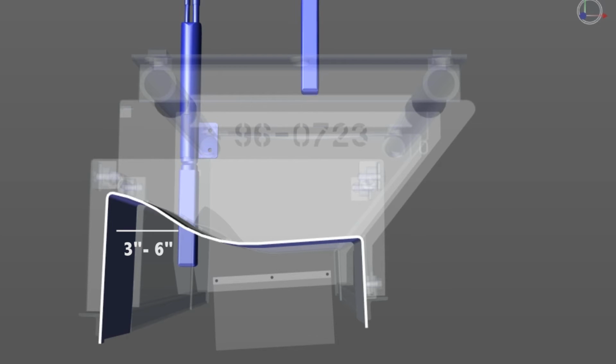Rollover curb is very similar to curb and gutter. Place a vibrator 3 to 6 inches from the back side of the mold. Add another vibrator 3 to 6 inches from the toe. Again, add a third vibrator if your mold is more than 30 inches wide.